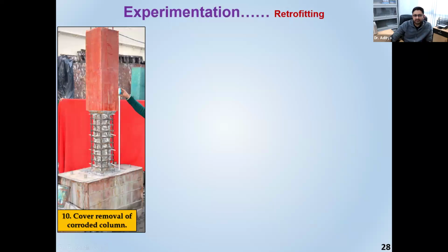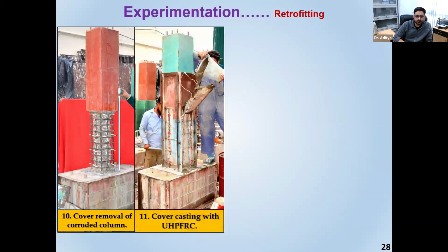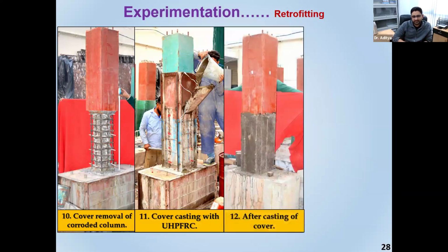Now, after this stage, there can be different ways of retrofitting, and their efficacy may obviously differ. We chose to go with a convenient one, which is to restore its cross section with a higher grade of concrete which has some flexural strength as well, with some fiber. That we call UHPFRC. You can see over here, we are pouring it again after applying the molding. After pouring, we recovered the cross section once again. But now this concrete at the cover is the UHPFRC concrete. On the core, obviously, it remains the same M30 grade normal concrete. So that was my retrofitted specimen.